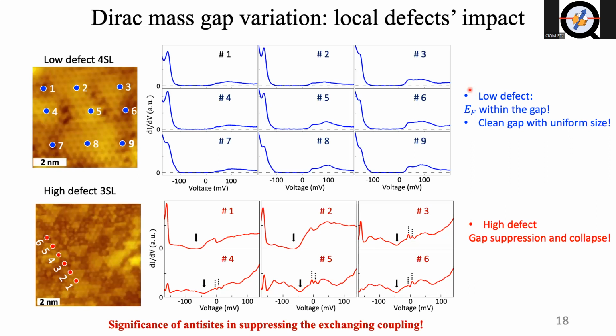Go ahead. Do the different defects have a similar contribution to the gapless feature, like the one you mentioned? There are some donors and also some acceptors. Yeah, that's also a good question. As I said, with STM, the anti-site defect we can see is mostly the manganese bismuth anti-site. The bismuth manganese is far below the surface, so it's hard for us to make a correspondence, and the bismuth tellurium anti-site doesn't quite exist in our sample growth. So the relation we want to build is mostly related to the manganese bismuth anti-site. But that's a good point.